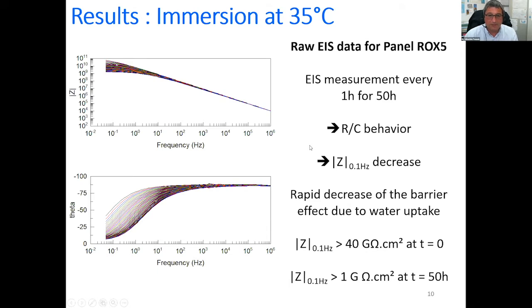So these are typical results for the ROX system, the panel 5, so ROX 5, for the immersion at 35 degrees C. As you can see, we performed some EIS measurements every 1 hour for 50 hours. We've got a typical RC behavior, and we can observe a decrease of the low frequency impedance modulus. This is a rapid decrease, of course, of the barrier effect due to the water penetration into the polymer network.